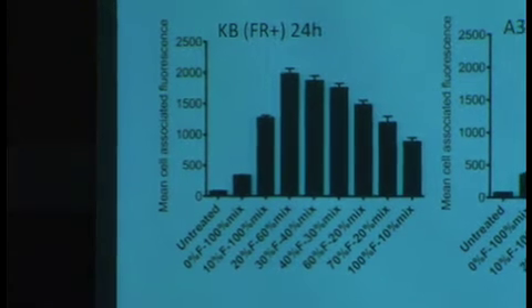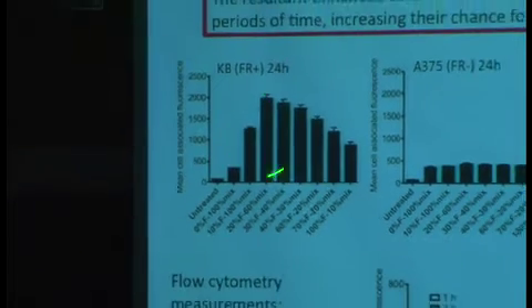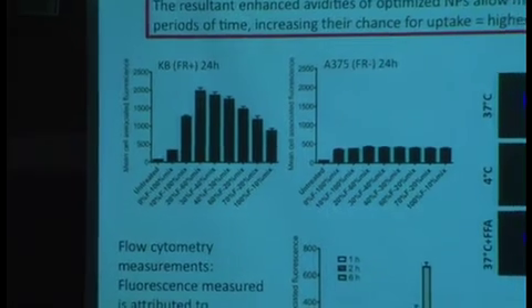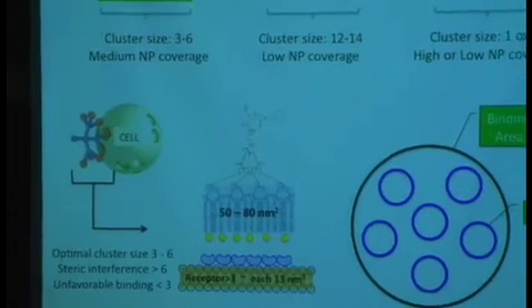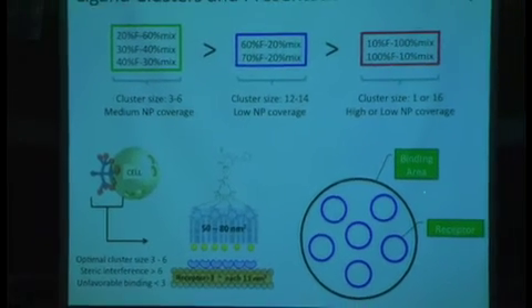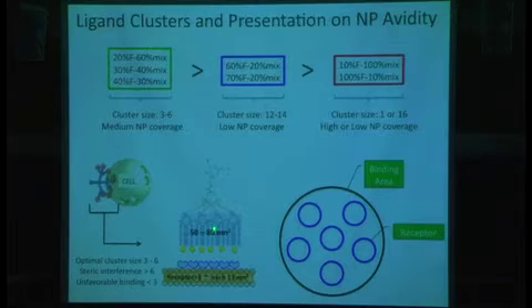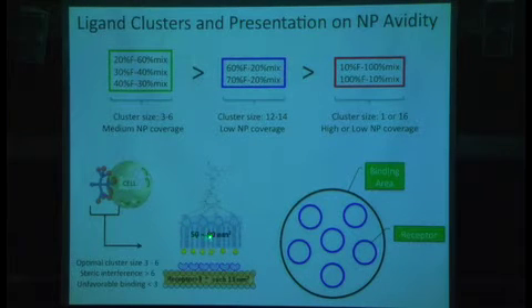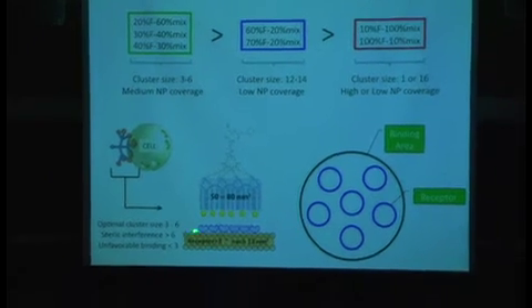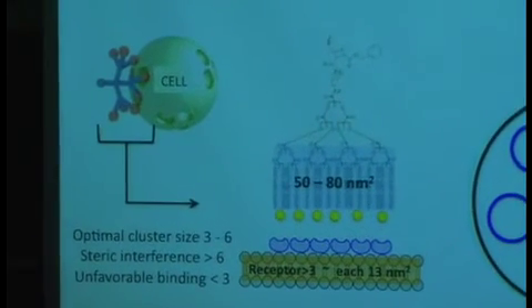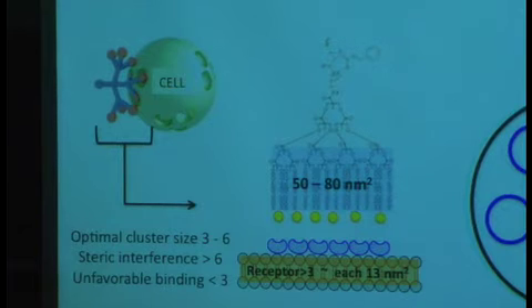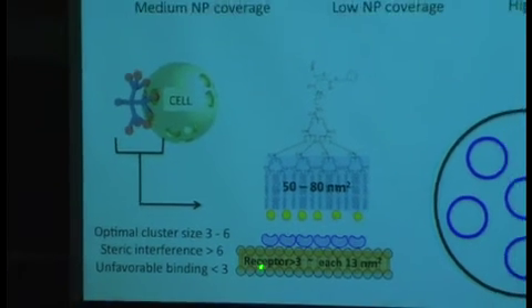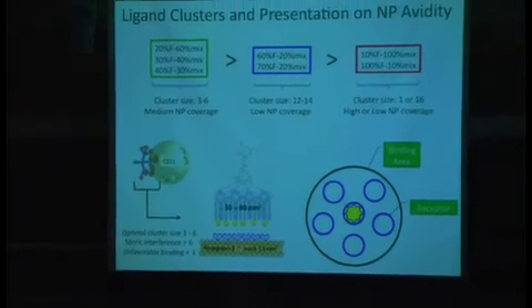We've done several experiments where we've looked at this with varying amounts of ligand density. However, the way in which ligand is presented can have an extreme effect. So this is, again, we've done several experiments in vitro. And if we think about what's happening, we believe that we have a dendron which actually presents an area to the cell membrane surface, which is roughly 50 to 80 nanometers squared. These are micellar systems. Because they form these micelles, we can think of this as a roughly average 90 nanometer micelle. There's going to be some curvature effects, but if we extrapolate, we have an area that is big enough to take up about 5 to 6 of these folate receptors based on their estimated size.